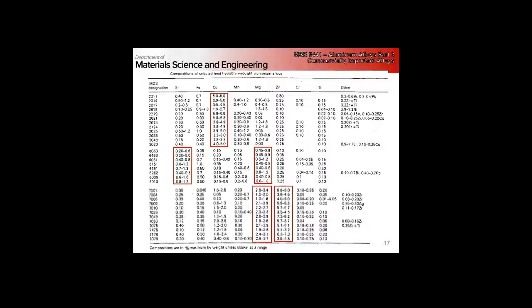So the compositions we're interested in are here. Notice that we tend to run from about 2% to 6%, maybe a little higher, copper in the 2000 series. Silicon we're generally less than about 1%, with about the same amount of magnesium. We tend to keep those pretty balanced so that the overall composition is about 1.2 to 1.5% of silicon and magnesium, and then 7,000 series with magnesium and zinc.